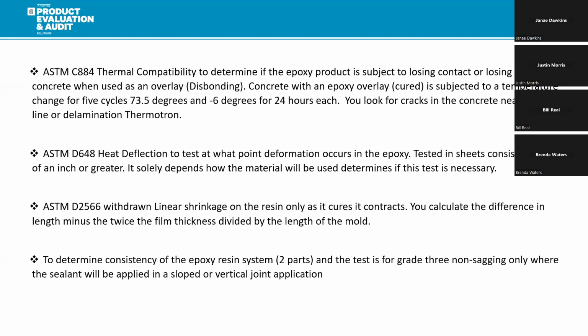You want to look for any delineation or delamination because you'll have that separating from the concrete. Also, heat deflection, ASTM D648, tests at what point deformation occurs in the epoxy. This is tested in sheets of 1/8 of an inch or greater, and how the material will be used determines if this test is necessary. So you won't need to do this test for all class types.